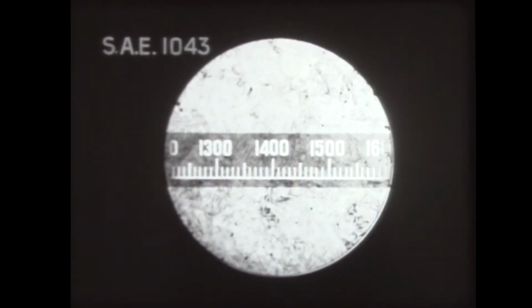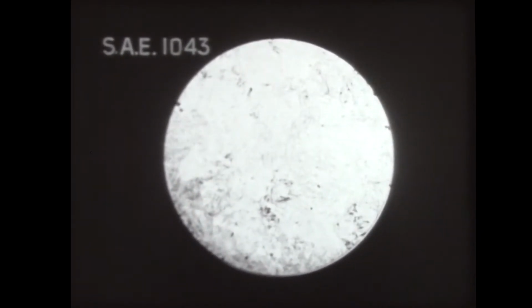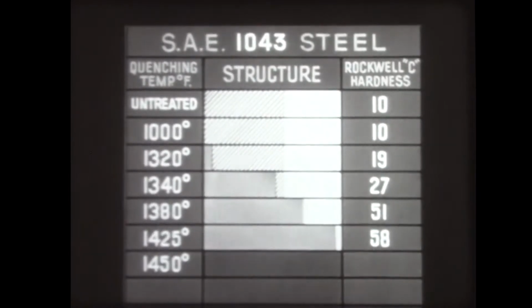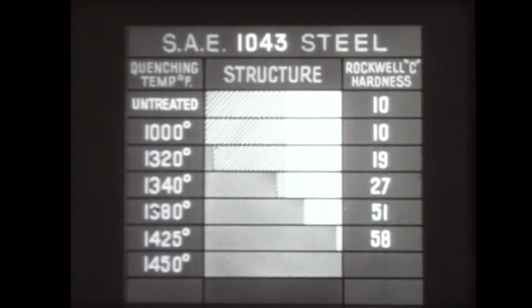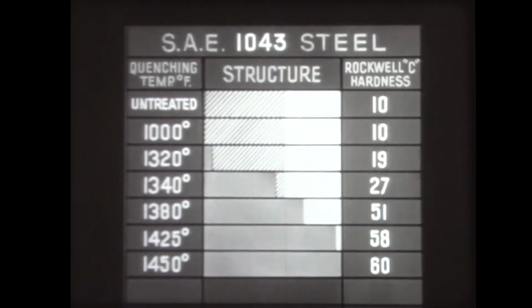When the steel is heated to 1,450 degrees and quenched, a wholly martensitic structure is achieved. This structure gives the highest hardness obtainable in this steel by this kind of heat treatment. Quenched from 1,450 degrees, its structure all martensite, the steel's hardness is 60. This completes our record of the S.A.E. 1043 steel.